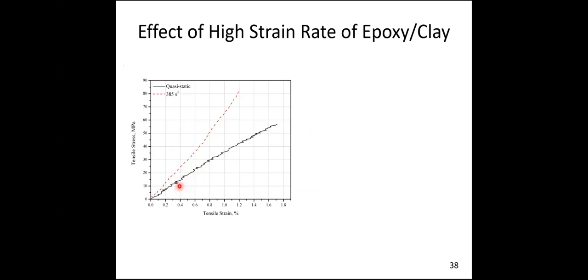So if you see, this black shows the testing was done at low speed, that is at quasi-static. It failed at around 50 megapascal, with a strain of 1.6%. Now, if you do the same sample at high speed, you can see a drastic increase in the strength. It has gone from 50 to 80. Again, the strain has been reduced, and the stiffness is increased.